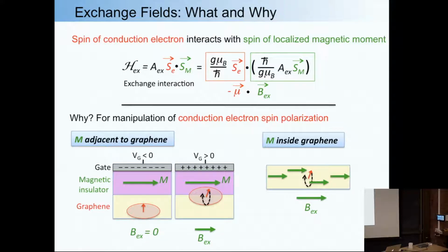And just by changing this voltage, you could change this internal or local magnetic field. It's an effective field. Or you could have the magnetization inside the graphene, and then this electron spin can interact with all these magnetic moments, and you could have spin precession. So if you have this exchange field, you can have spin precession, and you can manipulate those spins.